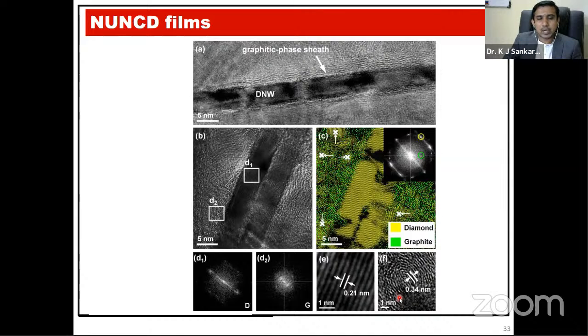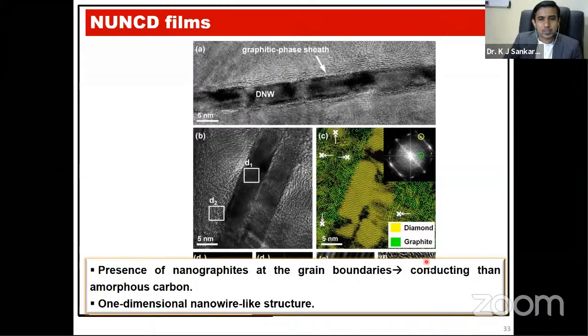So the presence of graphitic phases in the grain boundaries, as well as the one-dimensional wire-like morphological nature, helps to emit the electrons very easily. That makes a conducting diamond for the nitrogen doped ultrananocrystalline diamond films. The presence of nanographite at the grain boundaries makes the films more conducting compared with amorphous carbon, and also the one-dimensional nanowire-like morphology improves the aspect ratios, which makes NUNCD films conducting in nature with efficient electron emission. So far I have shown only the flat films with wire-like morphology.